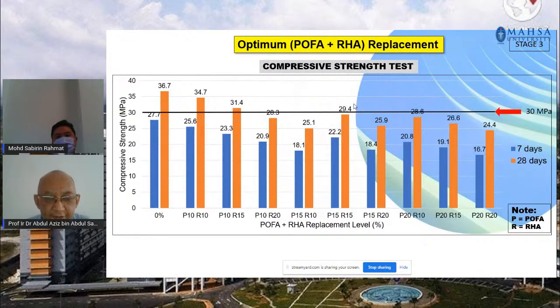Now this is stage 3 of the study, where we are combining the optimum POFA and the optimum RHA as replacement. So what we did was we combined various percentages of palm oil fuel ash and rice-husk ash in the mix. For example, we have 10% POFA and 10% rice-husk ash in this mix, and then it goes right to the end where we have palm oil fuel ash and rice-husk ash at 20% each. So basically, you're talking about 40% of waste material in this particular